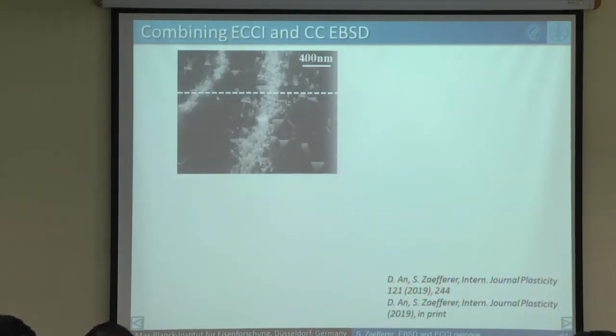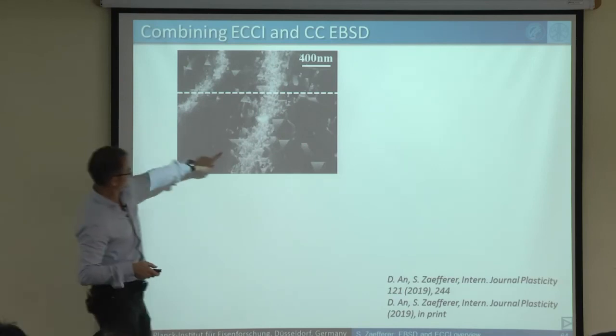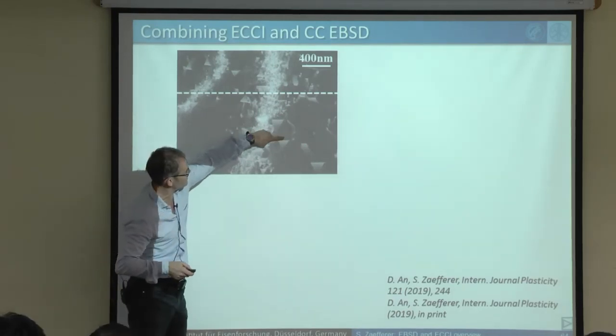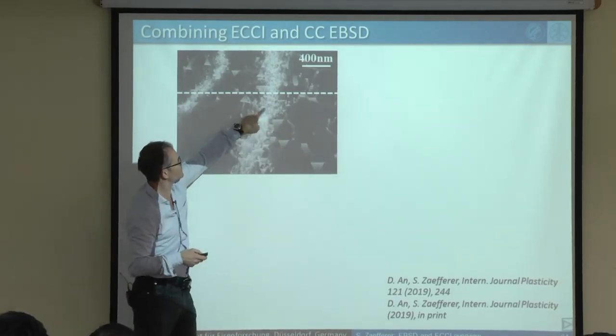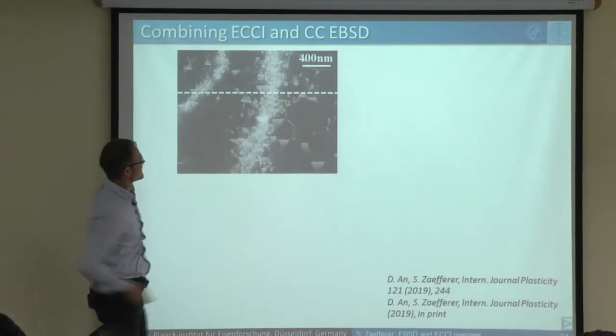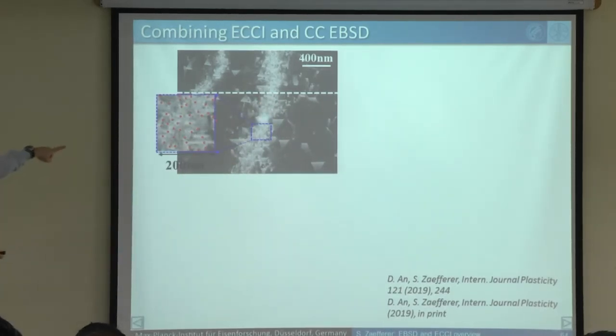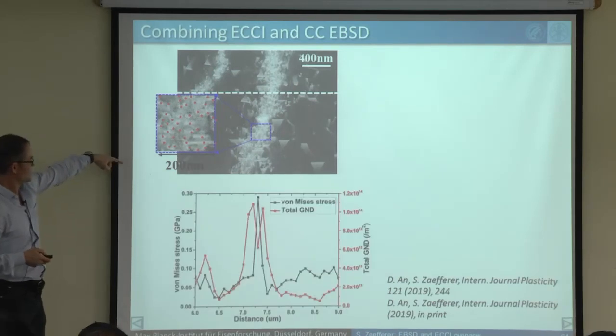So we are able to calculate that, and we can then combine ECCI and this cross-correlation EBSD measurements. And here you see with ECCI, you see all the little stacking faults with dislocations being split up, and you see all the individual very dense dislocations, and we can calculate from this the dislocation density.